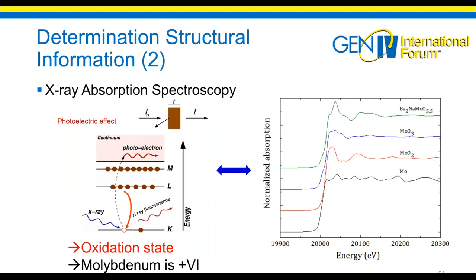And finally, another method has been used on this compound, called X-ray absorption spectroscopy. So the absorption of X-rays at a specified energy induces the ejection, that you can see here, of an electron from the core. And this corresponds to a jump in the absorption curve. And this jump is characteristic of the oxidation state of the chemical elements. So we performed this for our quaternary compounds.